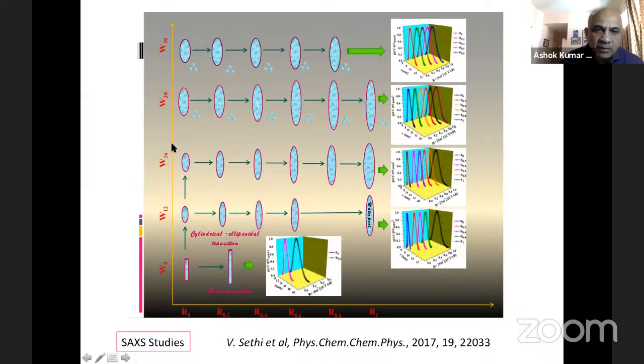So if you vary W naught and you vary some other ions to affect the interface, from small angle scattering you actually get these plots. And from that, you do some modeling, and you can get the size and shape of these droplets. So as the W naught parameter is increased, the droplet size is increasing. Here R is some ion we have added to affect the interface.